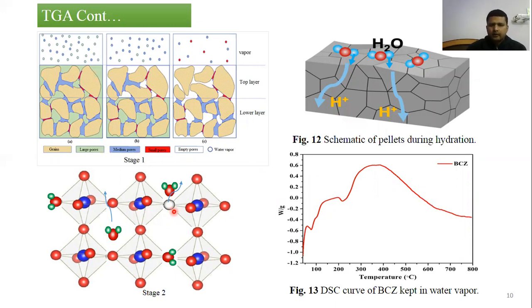The same can be explained as we observed in the DSC curves of the sample. Upon hydration, the water molecules can get absorbed at the surface, in the pores, and in the lattice site. Upon heating, we observe an endothermic peak around 100 degrees Celsius, which shows the loss of physical water from the surface and pores. Another endothermic peak is observed after 200 degrees Celsius, which generally corresponds to the loss of structural water from the lattice.